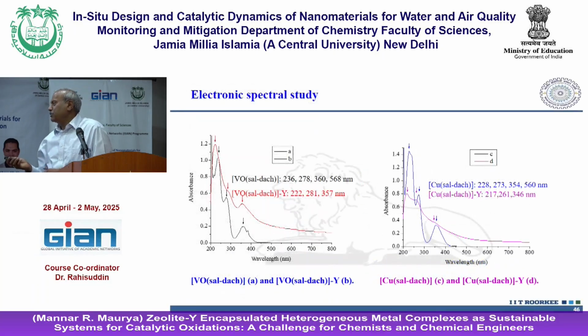Then UV-visible spectroscopy gives very good information. We are able to see the band due to the copper compound and the vanadium compound, so the charge transfer transition can be seen very nicely. The only thing is you have to record it in suspension, or in a mull, paste it and view it. You can record it. So that's a good part.